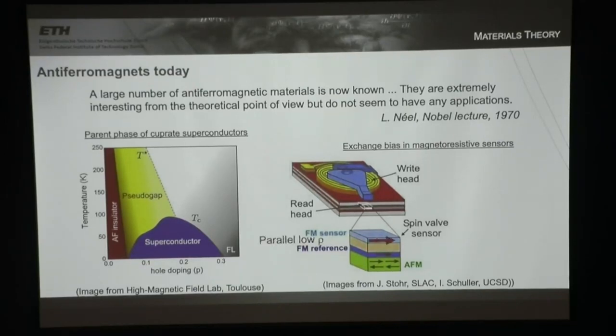And what happens is when the sensor is parallel to the reference layer, there's a low resistivity. There's not much scattering of the electrons because they're going through layers of the same spin. Whereas if the thing that's being sensed switches the orientation of the ferromagnetism in the sensor, so it's opposite to the reference, we have a high resistivity. The electrons which are carrying the spins get scattered a lot.